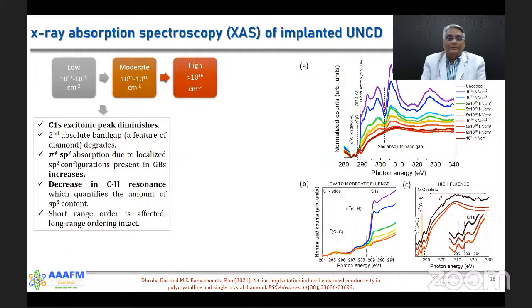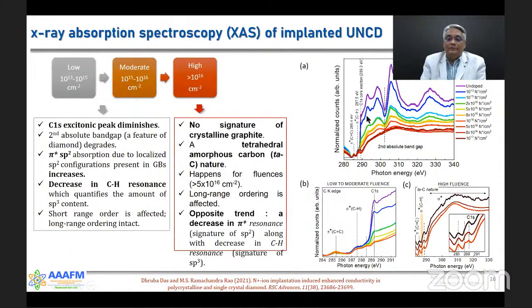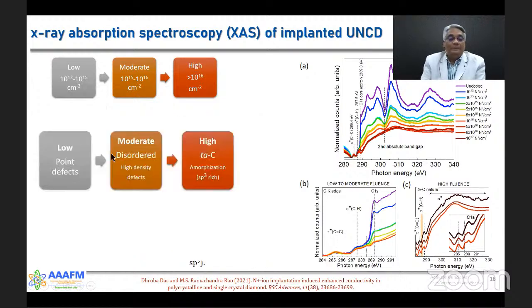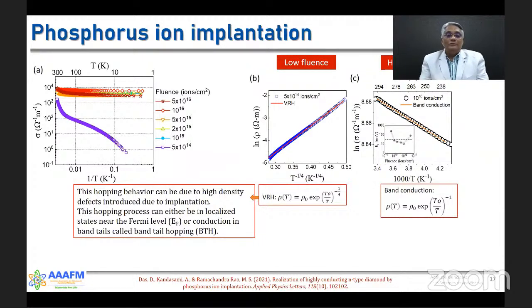A quick look at the X-ray absorption spectroscopy of implanted UNCD shows that the C1s excitonic peak diminishes, and then in the higher doping or implanted regimes, you see no signature of crystalline graphite. So low point defects, moderate disorder to high TAC content as you move from the low to high implantation regimes. Coming to phosphorus implantation, we see a similar result as in the case of nitrogen.